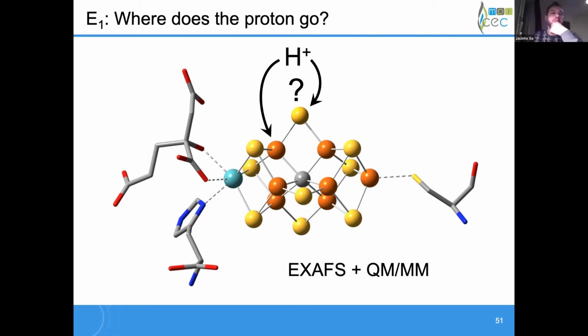And Yulia asked about what was the temperature that you did. Sorry, can I ask myself, because I have several questions and lack of details made it difficult for me to follow. First of all, this X-ray induced damage experiment, what was the temperature? About 10 to 15 K. And did you try other temperatures? Well, are you asking about when we were doing HERFD measurements, or in terms of determining our total scan time, or are you talking about the irradiation experiments? It doesn't matter, because I feel you just have not been damaging it at optimal conditions. Are you asking again about the generation of the cryo-reduced samples? The cryo-reduced samples were not prepared at the synchrotron. They were prepared at 77 Kelvin using a cobalt-60 source.